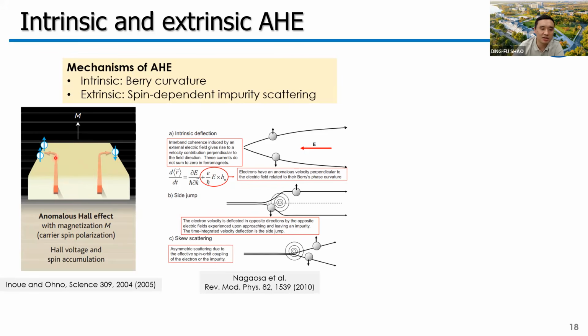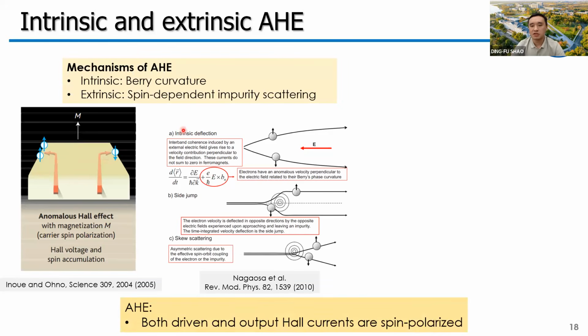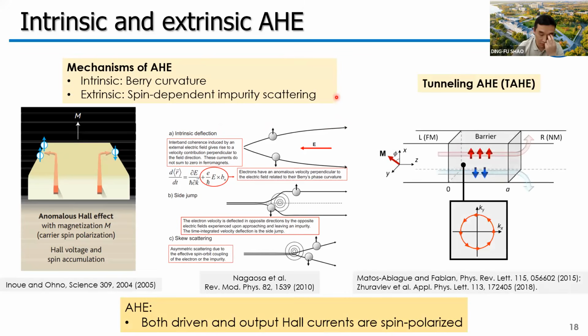And in this case, we can see the driven current is spin polarized. The output Hall current is also spin polarized. Recently, people found the anomalous Hall effect can not only emerge in bulk metals, but also emerge in TAHE junctions, where the left ferromagnetic electrode and the right normal metal electrode are separated by a tunneling barrier with a strong spin orbital splitting.